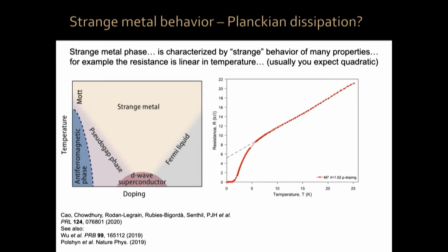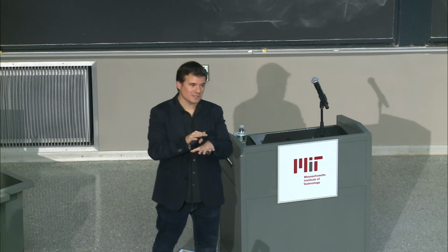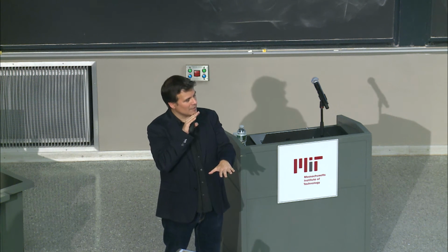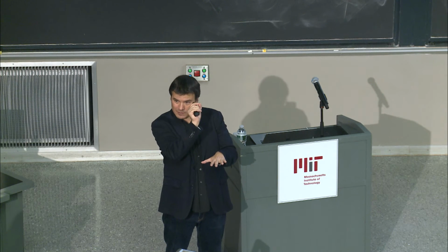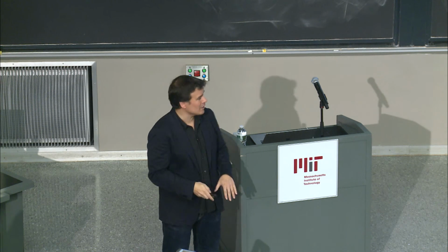So this is actually resistance versus temperature for magic angle graphene. You can see it's linear until it becomes superconducting. Of course, once it becomes superconducting, it goes to 0. But remember, we can tune everything in these systems, or in particular, we can choose a device with a twist angle such that the superconductivity is tiny.